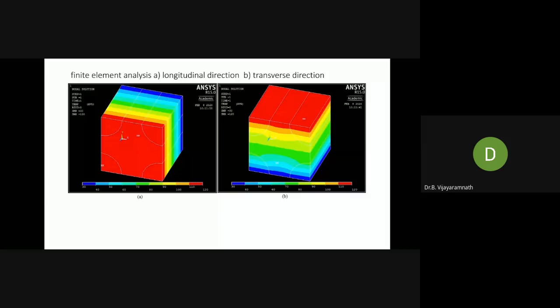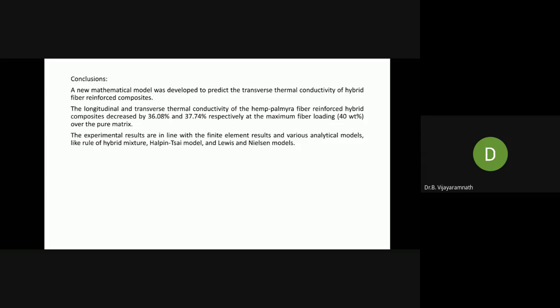So finally, I would like to conclude that we have generated a new mathematical model to predict the transverse thermal conductivity of the selected hybrid fiber reinforced composite. As previously conveyed, the longitudinal and transverse thermal conductivities of this composite have decreased by 36.08 and 37.74 at a maximum fiber loading. And finally, the experimental results are in line with the other analytical models as well as the FEA models.